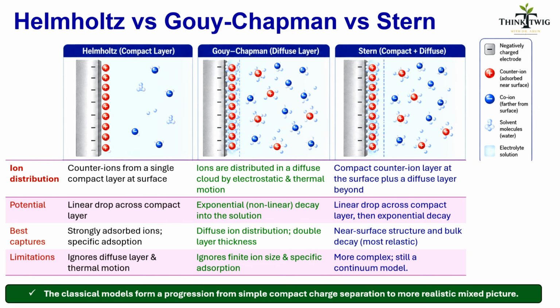Now let us place the three models together. The Helmholtz model gives the simplest picture. It assumes that the counter charge forms one compact layer near the electrode, and the potential decreases approximately linearly across that layer. And the Gouy-Chapman model introduces thermal motion. It describes ions as a diffuse cloud and the potential as a non-linear decay into the electrolyte. The Stern model combines both. It contains a compact region near the surface and a diffuse region beyond it.